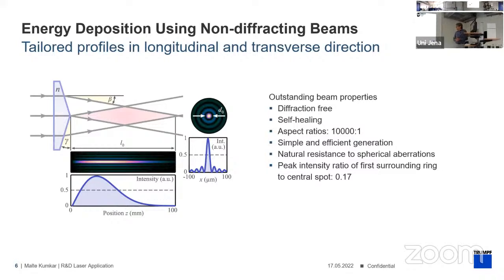Okay, we have these energy deposition by non-diffracting beams. The standard one is the Bessel-Gaussian beam, and it's diffraction free, as mentioned. It's self-healing, so in case you have a disturbance, it will heal out. Aspect ratios as high as 10,000 by 1 possible, and it's a simple and efficient generation of these beams. So by using an axicon, for example. So it has a natural resistance to spherical aberrations due to the conical shape, and the peak intensity ratio of the first surrounding ring to the center ball it's 1 to 17%. So it's very attractive,